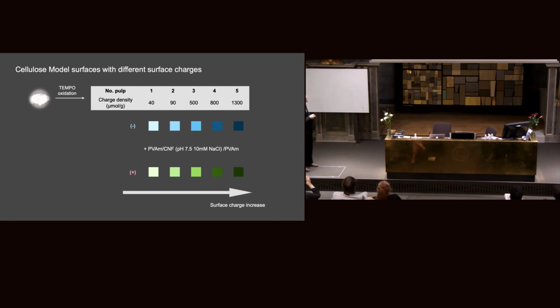To study that in a controlled way, we try to create surfaces with different charge, but exactly the same system. Therefore, we still borrow the concept using this cellulose model surface, and we coat the surface this time with different charge of the dissolved pulp, and then we modify those surfaces with PVAm, CNF, and PVAm.